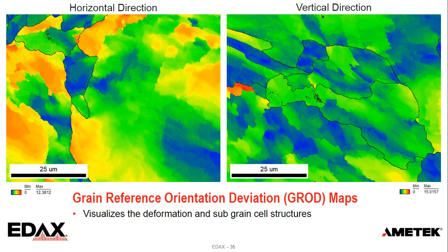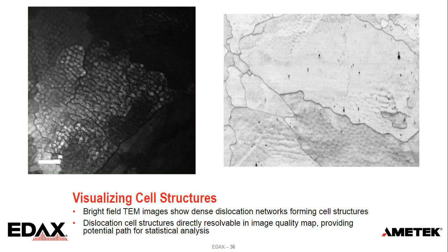Within the grains, you can start to see this kind of a cell subgrain structure, as a fingerprint of the deformation. And so we can compare this to TEM results. This is a bright field TEM image on the left, and you can see that cell structure pretty clearly. On the right, this is the image quality map from one of those higher magnification images. You can see we actually can detect some of that cell structure in the bottom just through the image quality as well, which I thought was really interesting.